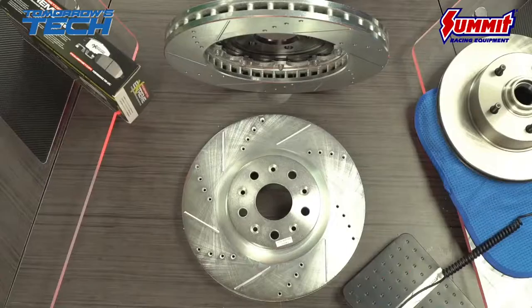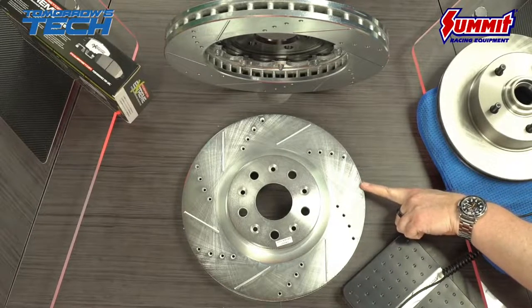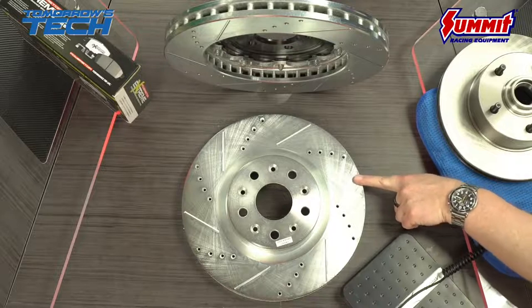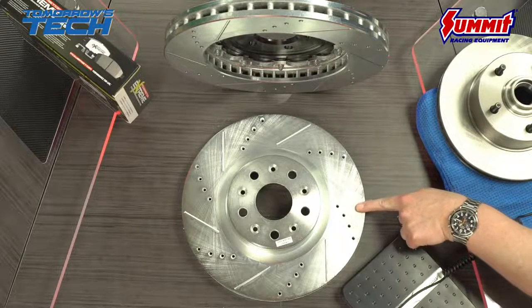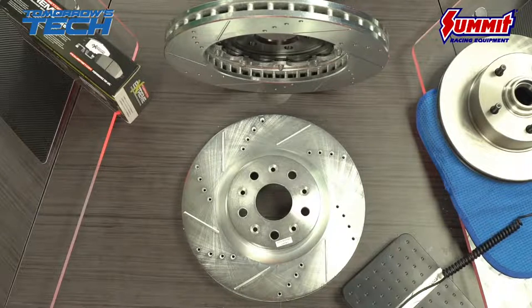From my experience, if you look at any brake rotor on the edge itself, it's always a chamfer too. They do that initially to eliminate a lot of the stress on the rotor itself, because if you have a nice sharp edge, that's where cracks tend to propagate more and take on more stress from the rest of the casting. The casting itself is under different stresses as it heats and cools, and the microstructures inside the metallurgy go in and out, in and out, and that can disturb a lot of the structure of the rotor. Eventually it will crack if the metal is just a little too hard.